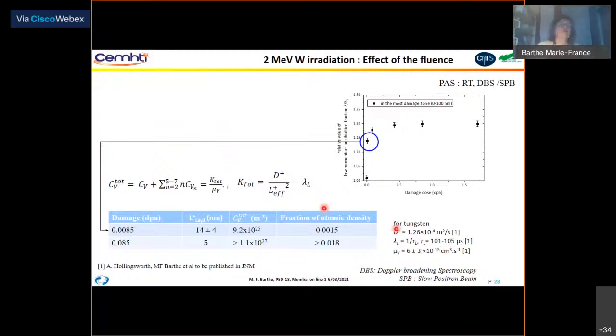And for the higher damage level, it is not possible to really extract the concentration because this effective diffusion length is very short, but we could say that it is higher than 10 to the 27 per cubic centimeter.